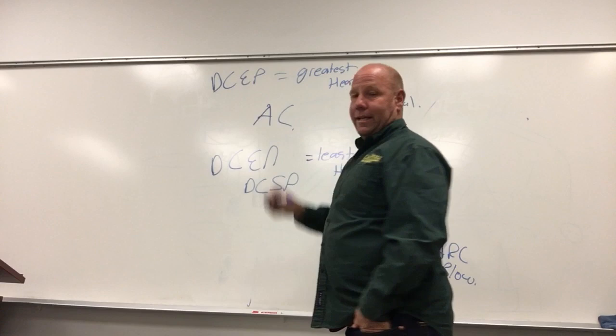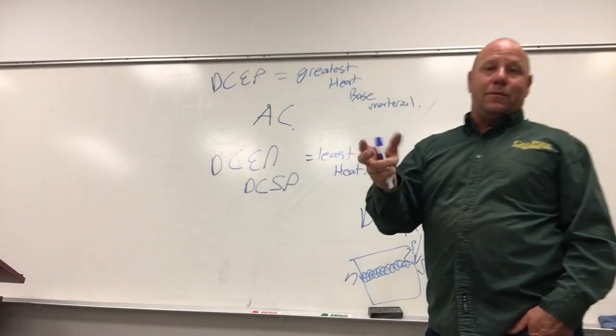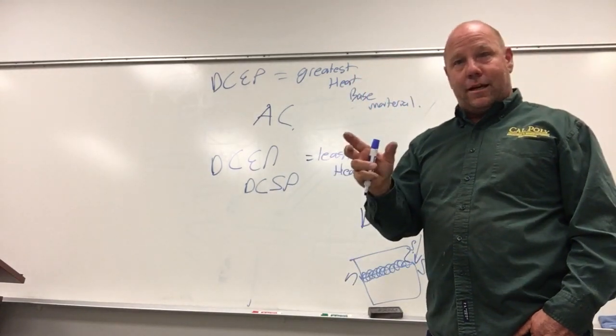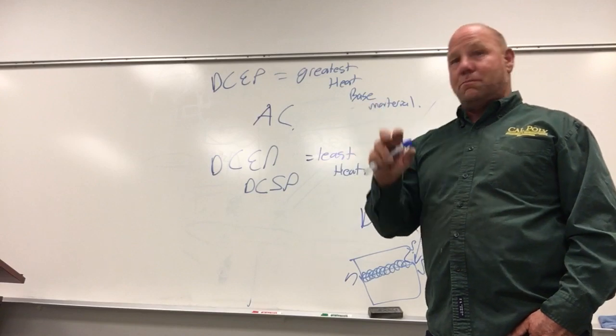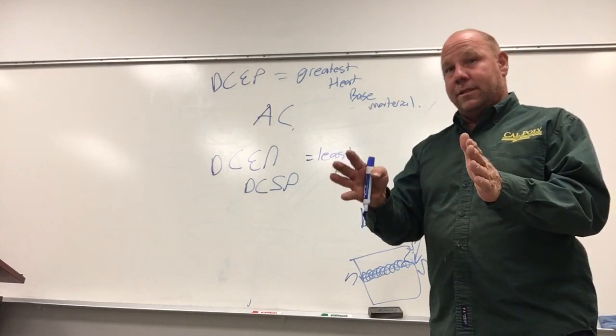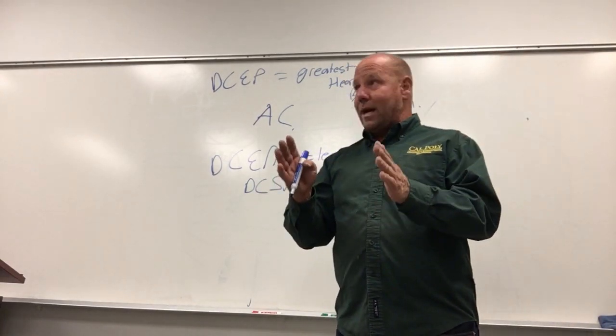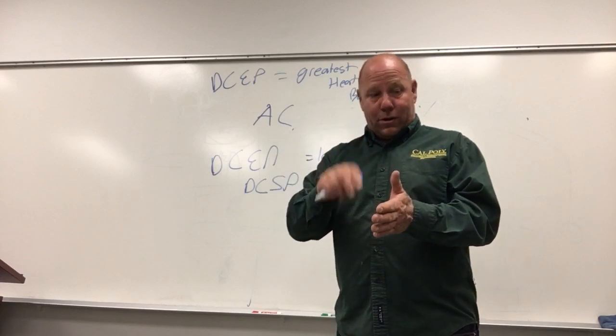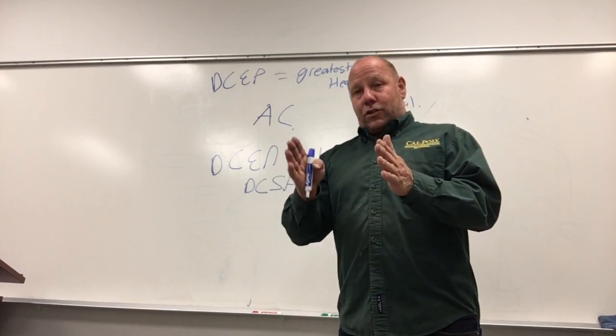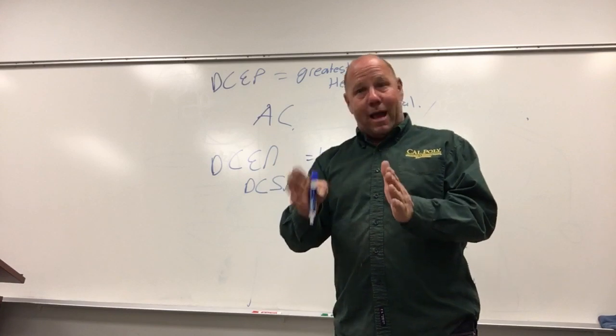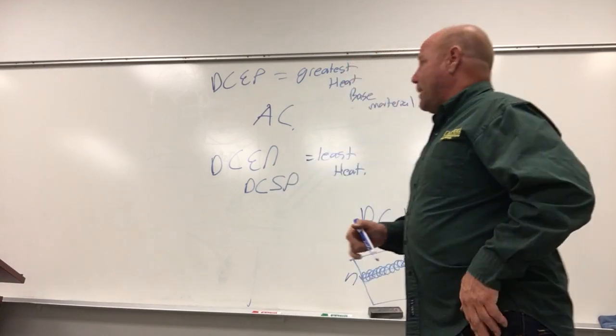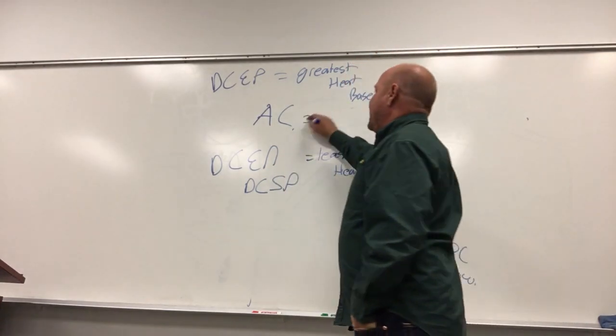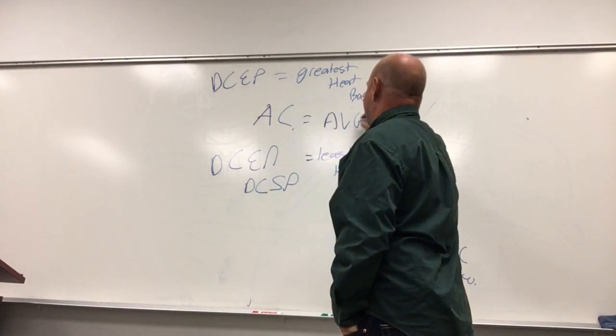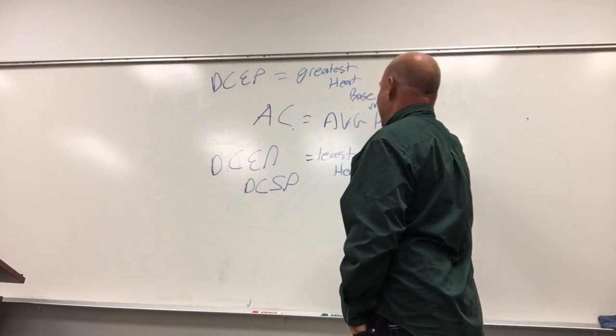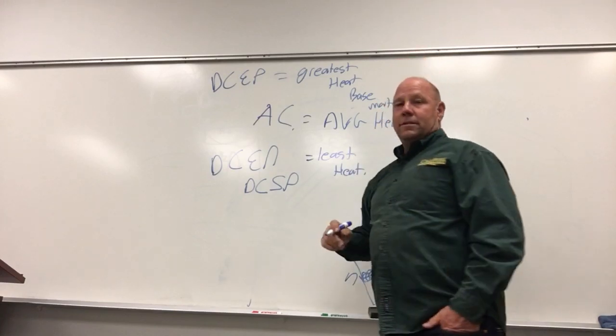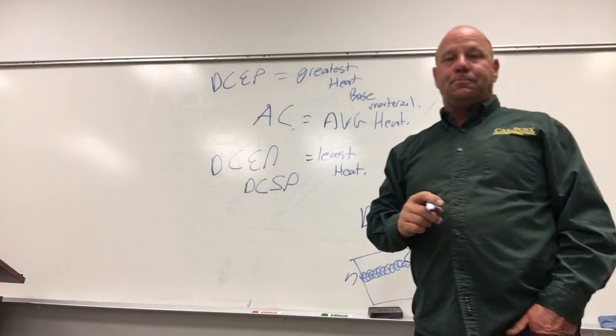One way that we can combat that, we can use AC. That flipping of the poles back and forth that AC causes will diminish a lot of those magnetic charging properties. Keep in mind, we'll still have the magnetic properties taking that ball across, but we're not going to have those charging properties, which makes it into a magnet. So AC is the way that we get out of arc blow. And AC really has the average penetration, so it has the average heat input into the plates.